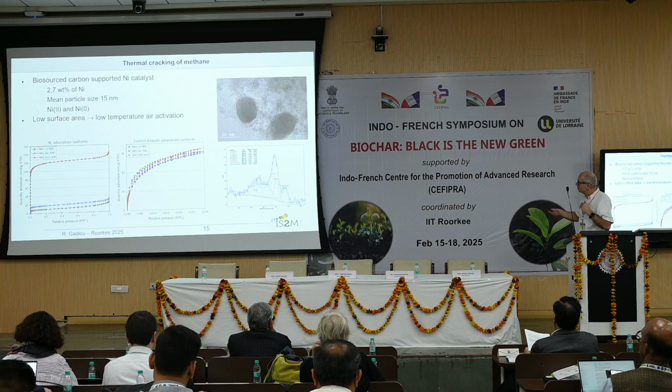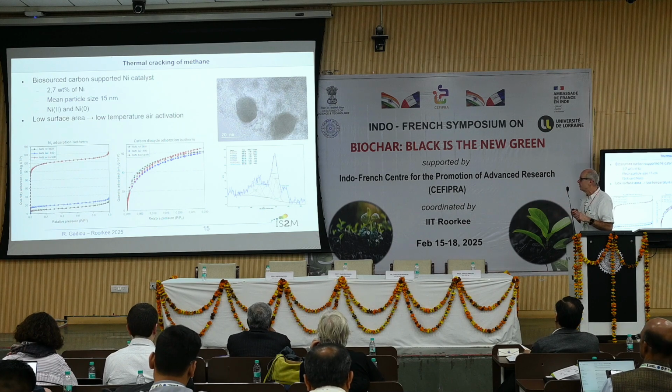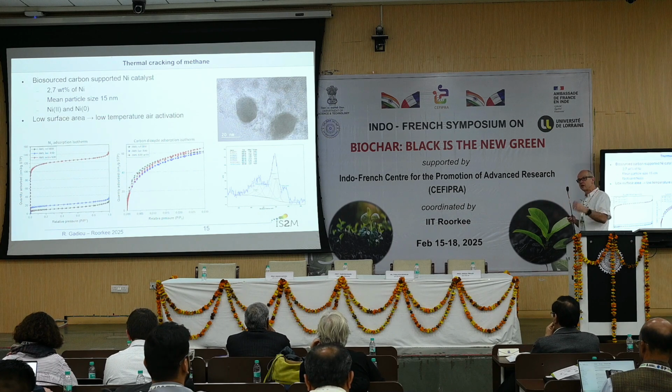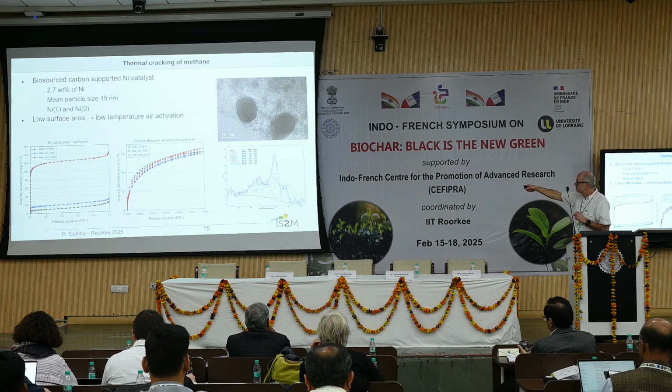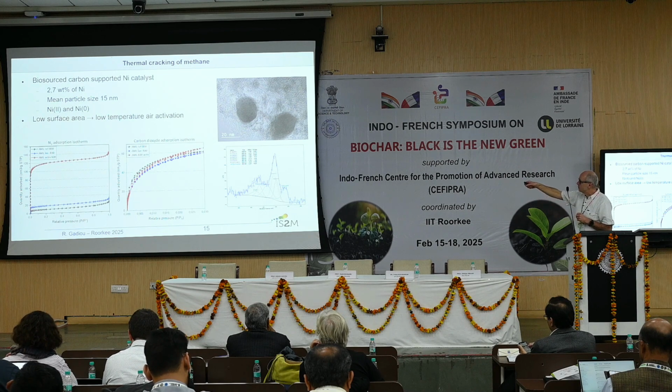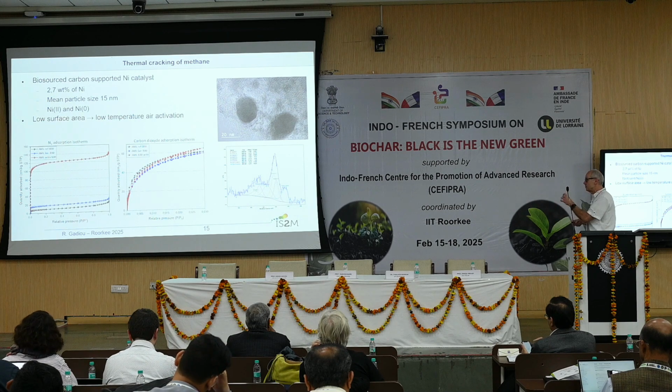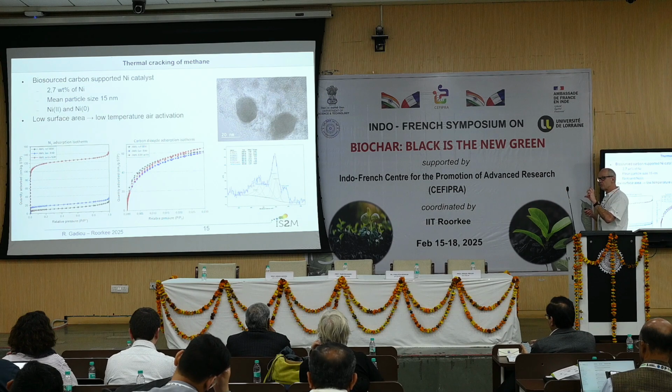And the second aspect is shown with the XPS analysis. We see that we have changed the speciation of our element. We have already some part, the peak on the left, which is nickel 2, but we have also nickel 0, which is the right part, the blue peak. This is also strongly related to the surface chemistry.